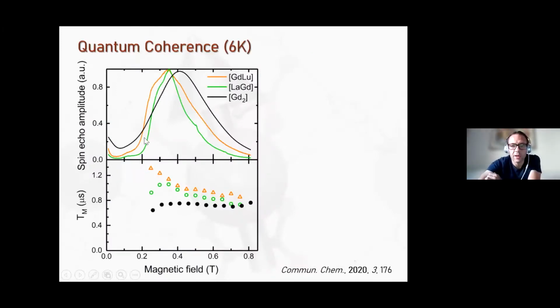This system shows coherence, so we can detect by pulse EPR the echo signals at different magnetic fields for the individual gadolinium ions, and also for the system where both metals are present. And these pulse EPR studies also allowed us to compare the quantum coherence at the various magnetic fields, so for the various transitions. For example, we can see that for the individual ions, the quantum coherence is always larger than when we have both gadoliniums present in the molecule.